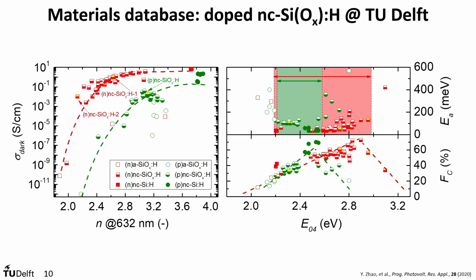And for all these, let's say, good materials, we saw that the crystalline fraction from Raman spectroscopy was always relatively higher. So this kind of proved the point that when we want to go for low activation energy materials, you need to develop nanocrystalline silicon layers with your plasma processes. Of course, I'm talking about silicon-based layers that in this way can help in getting higher and higher efficiency.